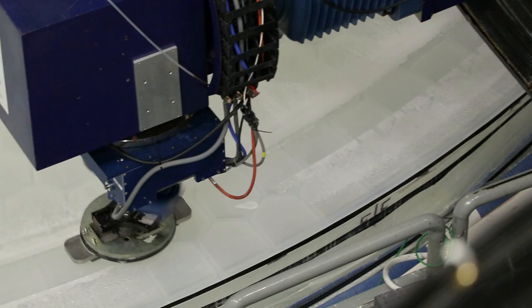After all that — after melting the glass in this giant oven and polishing it for two years — all you have is a huge, really smooth piece of glass. So the mirror lab actually doesn't make any mirrors. The final step in turning this giant piece of glass into a mirror is done on site at the observatory: a layer of aluminum about 100 nanometers thick is deposited onto the surface. To cover a mirror of this size, it only takes a soda can's worth of metal. Unlike your mirrors at home, the reflective coating is only on the front surface, so it's very delicate and needs to be re-aluminized every so many years.